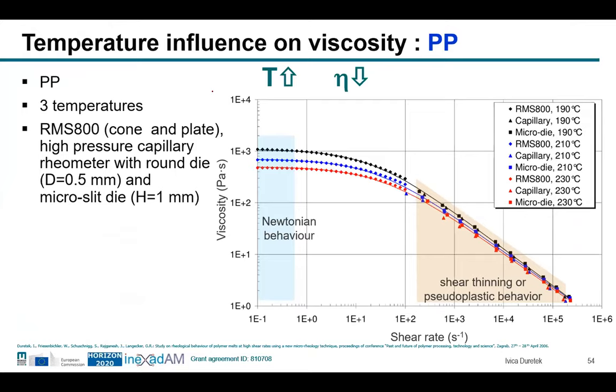For example, this is a typical viscosity diagram for one polypropylene. This viscosity curve was measured at three temperatures using two rheometers in the shear rate range up to 100. The measurements were done using the cone and plate rheometer, and at higher points we have used the high pressure capillary rheometer. You can clearly see that with increasing temperature, the viscosity decreases. And in this case of the polypropylene, we can measure the viscosity in a wide range of shear rates.